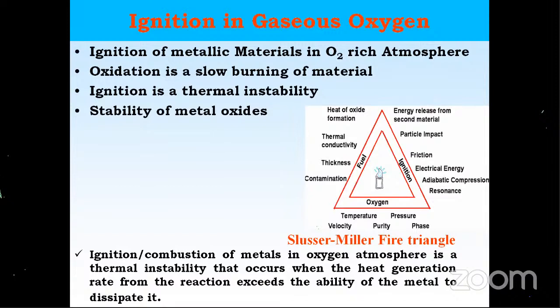Coming to the oxygen status: if the temperature is high, yes, it is more prone. Pressure is high, more prone. Velocity is high, more prone. Purity of oxygen, yes. Phase: if it is liquid phase, we don't have much issue, but if it's gaseous phase, yes, it's a problem. Then the ignition conditions: the energy released from the second material can cause ignition.